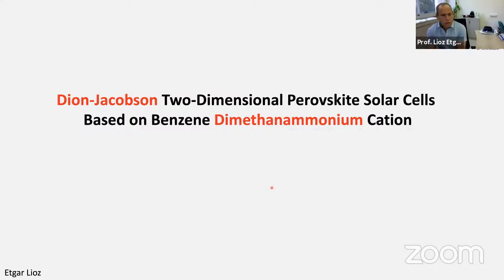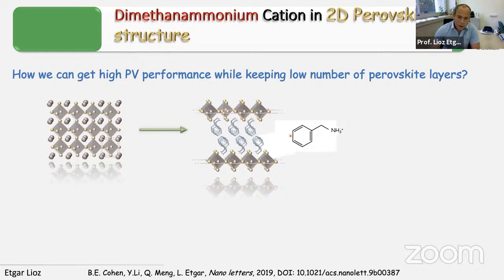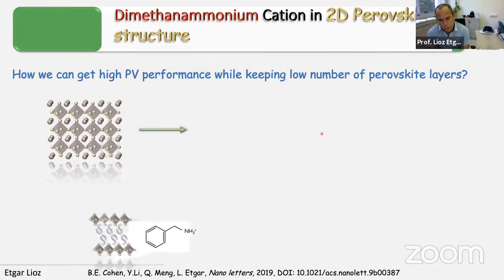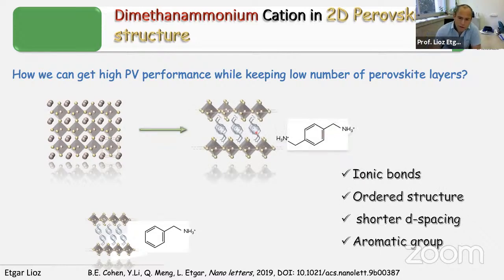And following this, we started to think of new cations that can improve the structure of the perovskite. From one side, improve stability. From the other side, make some organization of the layers on the substrate. And if so far the most common cations used just one ammonium group, as you can see here, it could be with benzene or any other carbon chain, we took a diamine group, and the main difference is that this diamine actually holds the inorganic framework by ionic bonding and not by van der Waals interaction. And this hopefully can make much more ordered structures than before and make the distance between the inorganic framework shorter. And I will start from the results.